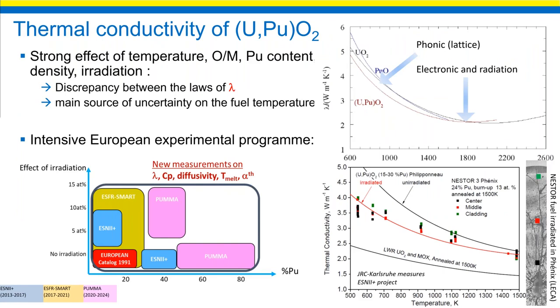The figure on the right upper side describes the general trend of the lambda with the temperature. It's composed of several contributions: the phonon conduction due to the lattice, effective at low temperature. And then after 1200 Kelvin, the electronic conduction as well as the radiation are much more effective and contribute to the increase of the global conductivity with the temperature.